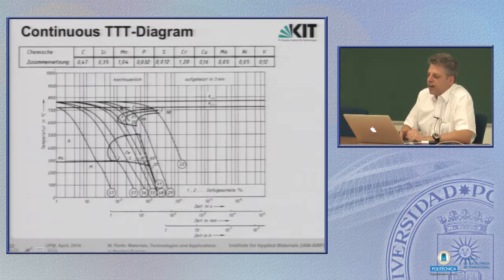The phase shows here F. This means ferrite or P, perlite. So if you do it slow enough, you can produce perlite from the one and the same steel. If you do it very quickly, then, for example, you follow this line, then you have a complete transformation from A, that's austenite, down to martensite. So if you do it fast enough, you will end up in 100% martensite. There is something in between, which I have called bainite, which we don't go further into detail here.